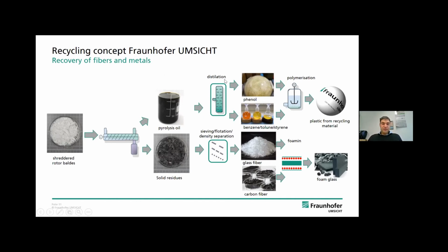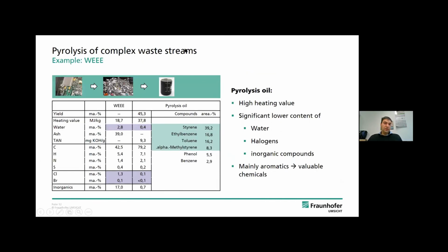But I want to focus a little bit more on the pyrolysis oil itself, because it's very important to understand what the composition of this pyrolysis oil is, to see how to go from the pyrolysis oil to a new product. And we did some analysis on the pyrolysis oil. In that case, we used, in my eyes, one of the most challenging waste streams. This is electronic waste, WEEE. And our analysis showed that we have a very high heating value in the oil.